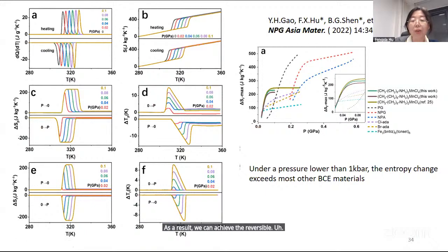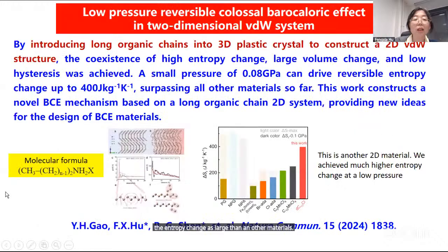As a result, we can achieve a large reversible entropy change at a very small pressure. At the pressure here, 0.08 GPa, the entropy change is larger than in other materials. Moreover, in the three-dimensional materials, we introduce long organic chains to construct a two-dimensional vdW structure. We achieved much larger reversible entropy change. The molecular formula is like this.